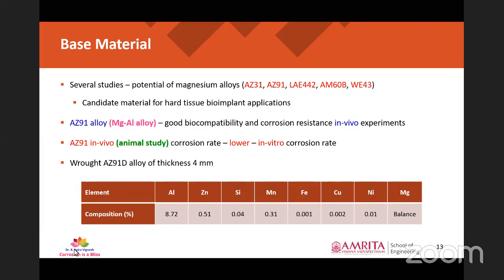In vivo animal studies, in vivo based corrosion rate experiments, indicated that the corrosion rate of AZ91 is less than the in vitro corrosion rate, which is based on cell culture based experiments. So in this study, we have taken a wrought AZ91D alloy of thickness 4 mm, whose composition is given here. AZ91, as you all know, is magnesium 90%, aluminum around 9% and zinc approximately 1%. These are the spectrometer readings showing the composition of the wrought AZ91 alloy purchased from the market. So we are going ahead with fabrication of a composite using this material.